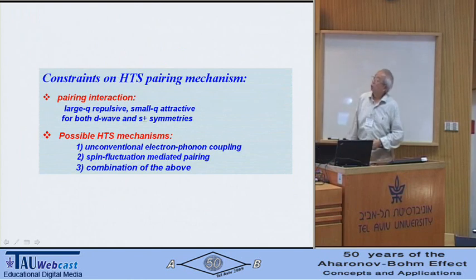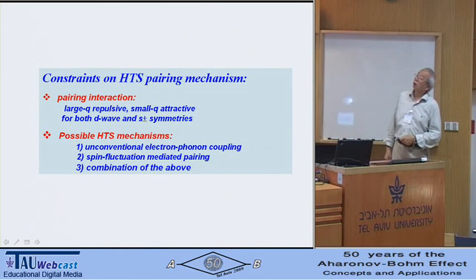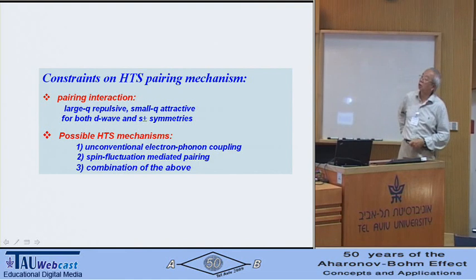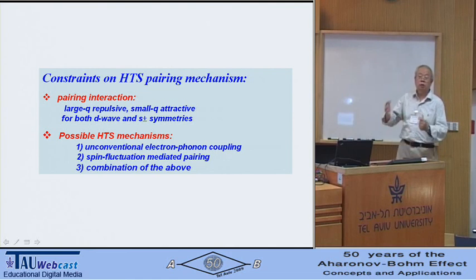So the constraint on high temperature superconductor pairing mechanism, this is what we really want to get a handle on. The basic message is to say that the pairing interaction has to be repulsive at large Q, attractive at small q. This applies for both D wave and S plus minus symmetry. Turns out they give you the same requirement.